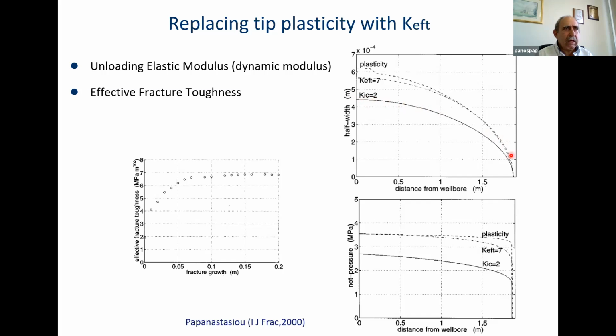So this is with elasticity, with effective fracture toughness, and with full plasticity. You can see here that the effective fracture toughness prediction is close to plasticity, and the same results we can get with the pressure profiles. The pressure profile predicted by the effective fracture toughness is quite close to plasticity.